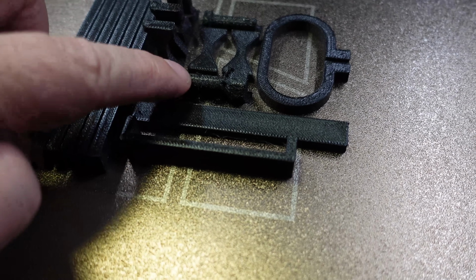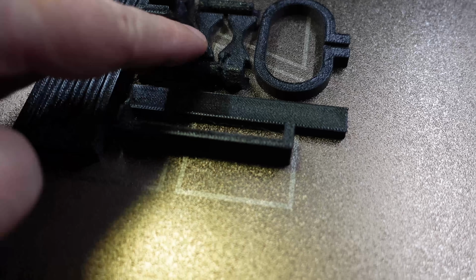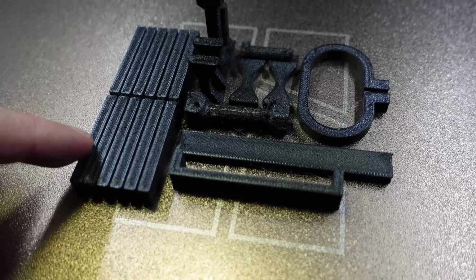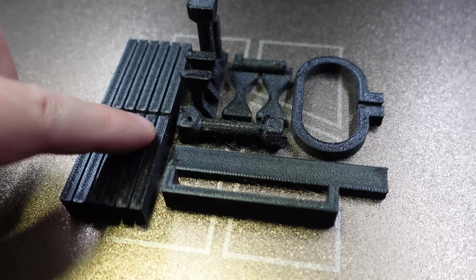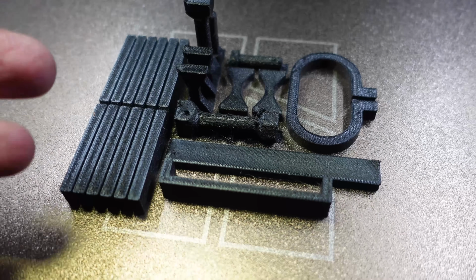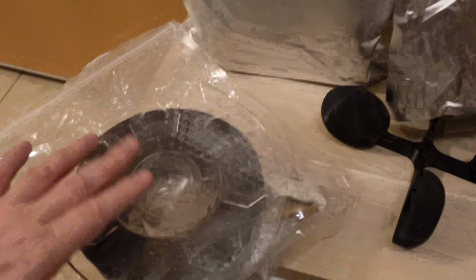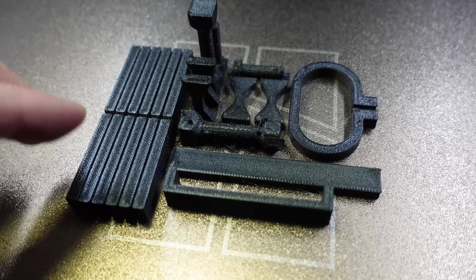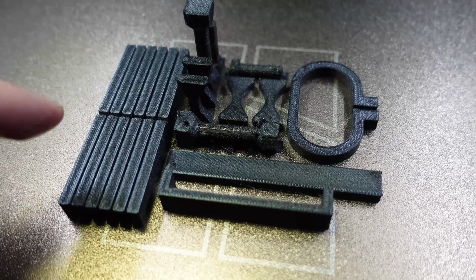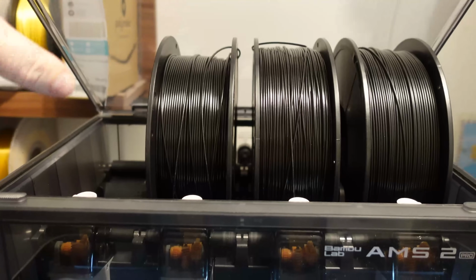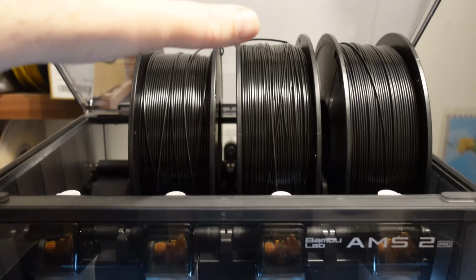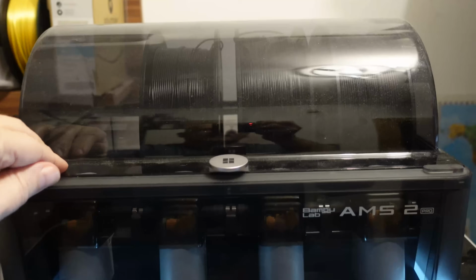This is what I was talking about. The printing is finished, but look at this surface, so definitely even out of the box it is full of moisture and needs to be dried. I think some kind of aluminium packaging would be better instead of this plastic foil. And I will stop the printing now, and all three remaining filaments will go into the dryer for at least 6 hours. I removed the PLA, and these are PETG, ABS and nylon, because they can be dried at a little bit higher temperature.